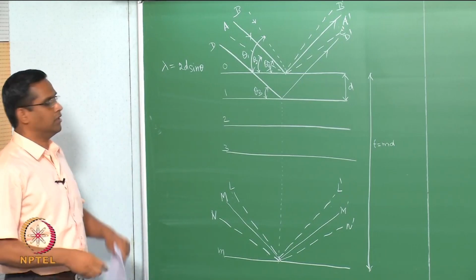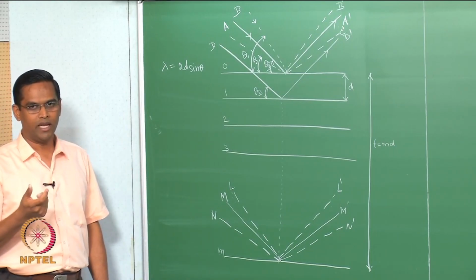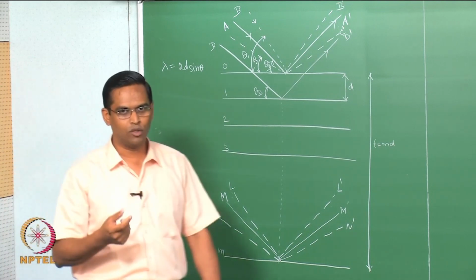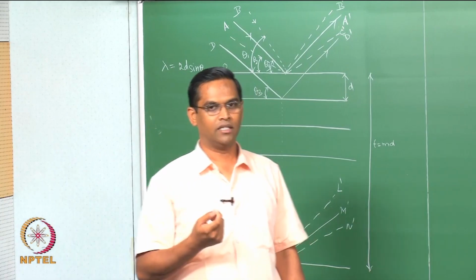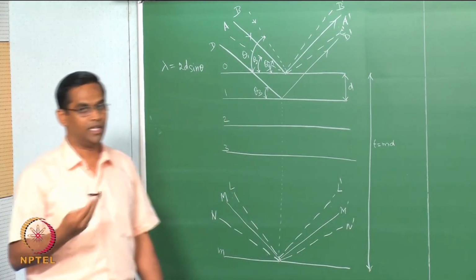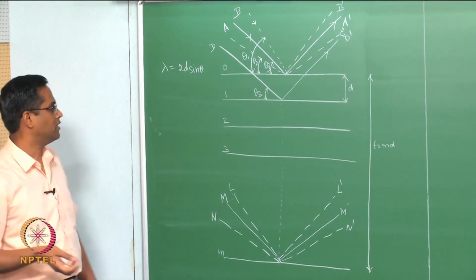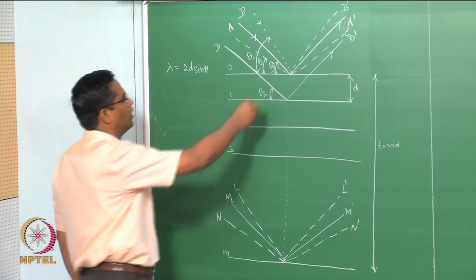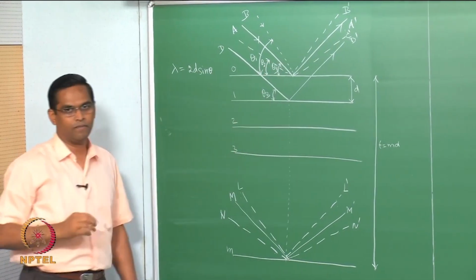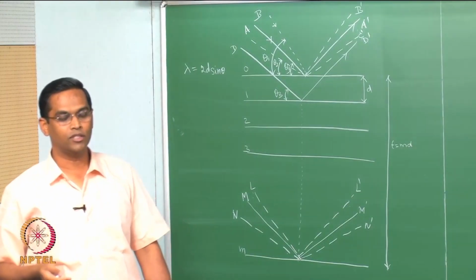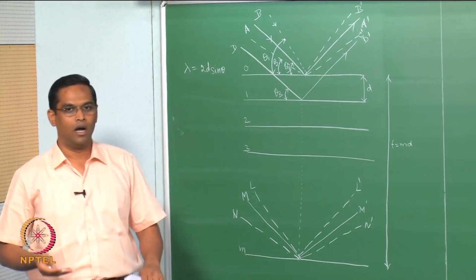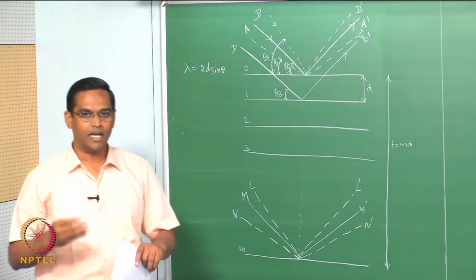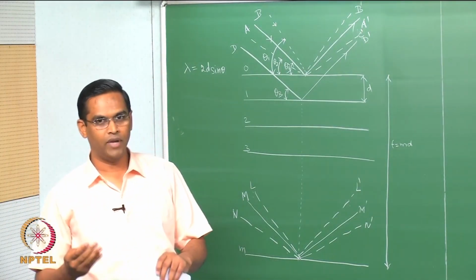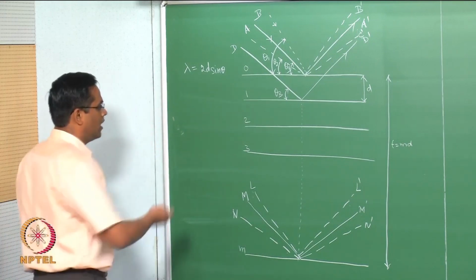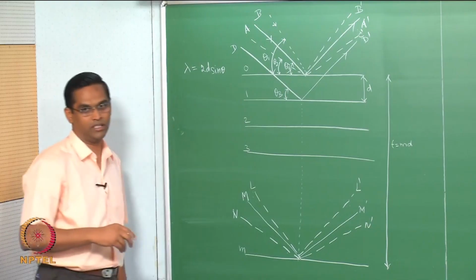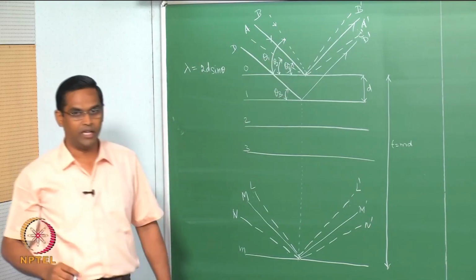Since it is slightly different from theta b, as I mentioned, the path difference also will be very small, a fraction of an integral multiple of lambda, not exactly an integral multiple of lambda. The consequence is this is not going to cause destructive interference. The plane which has atoms whose scattered beam will be exactly half the wavelength out of phase will be somewhere inside the depth of the crystal, which we are not seeing, because this theta is only fractionally varying.